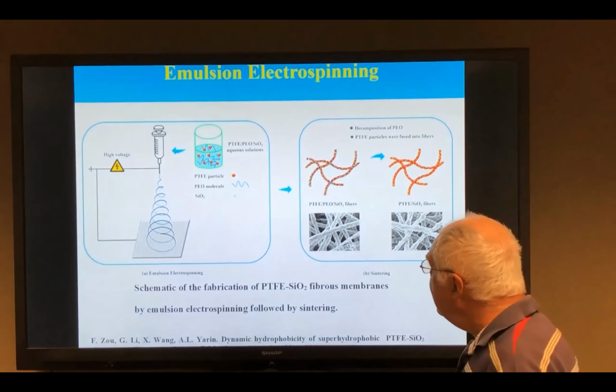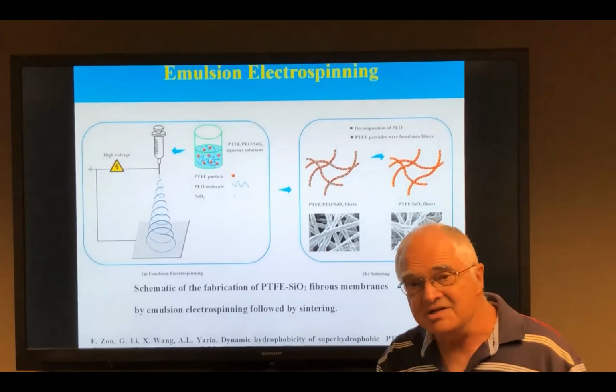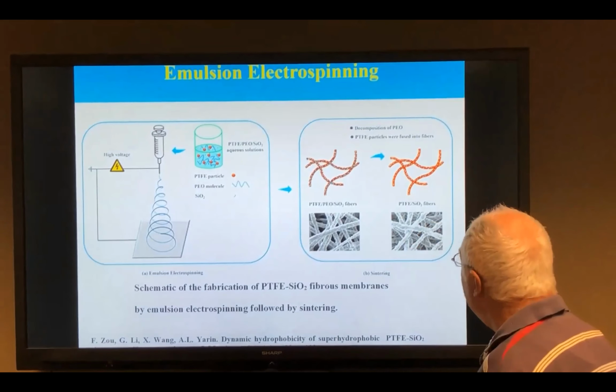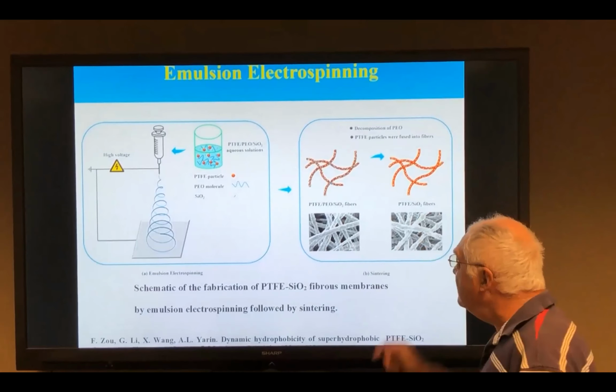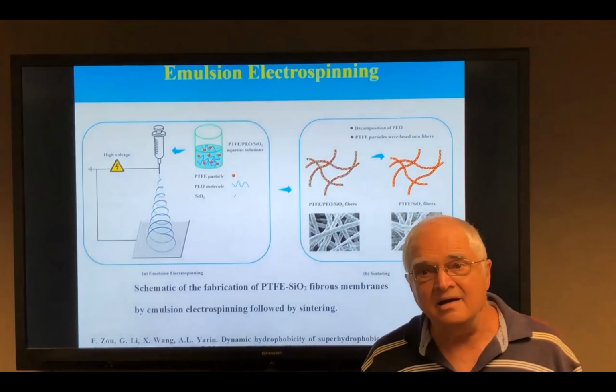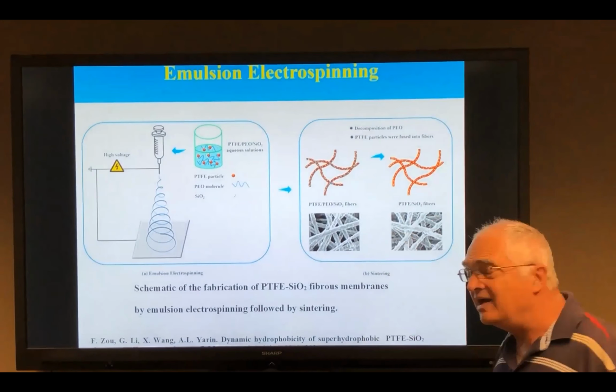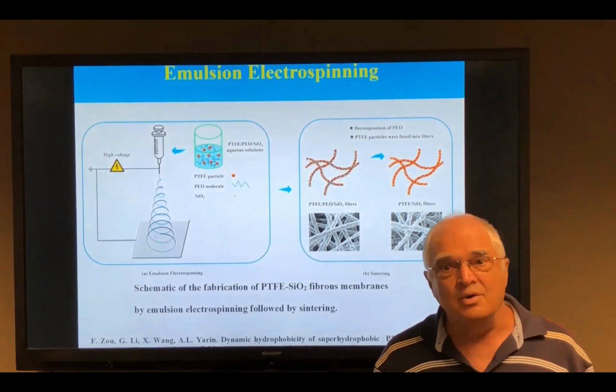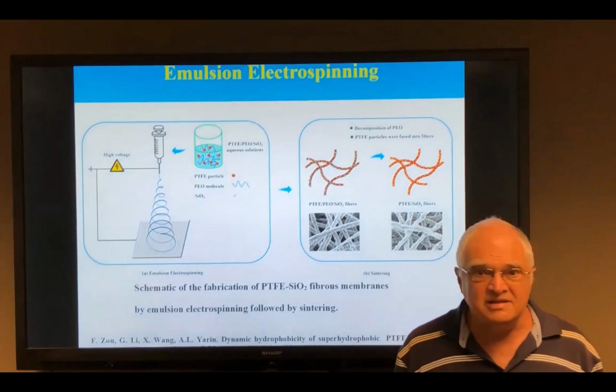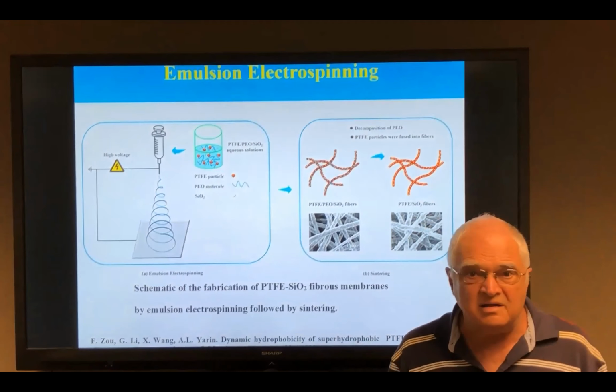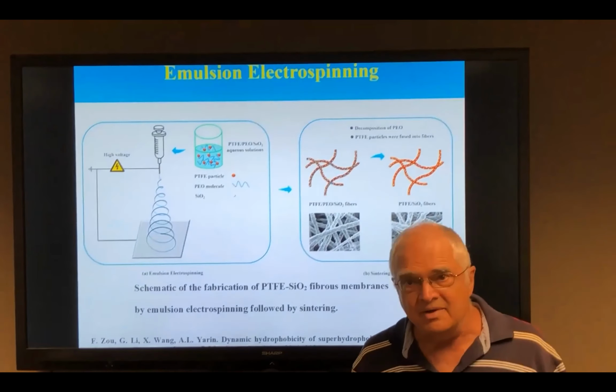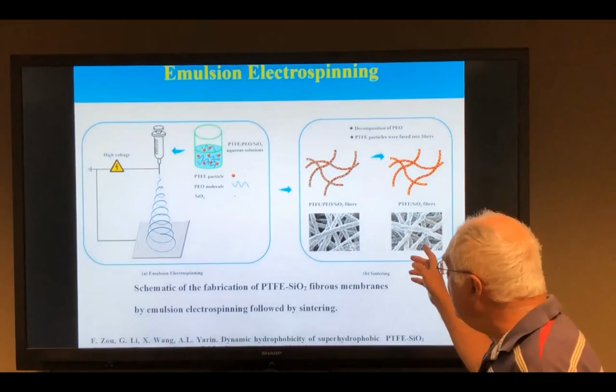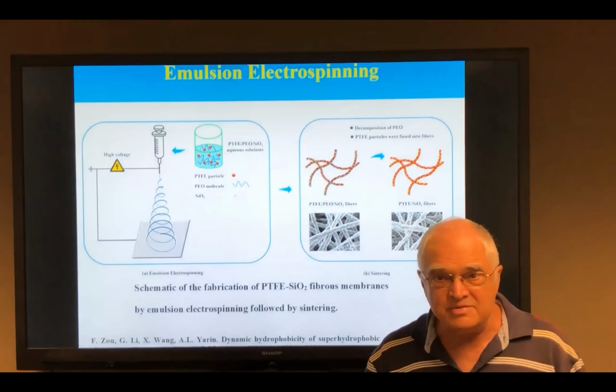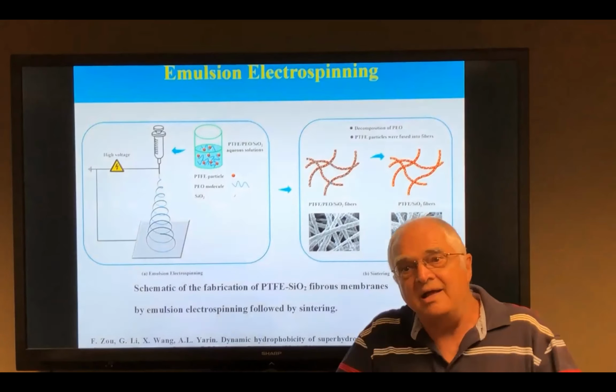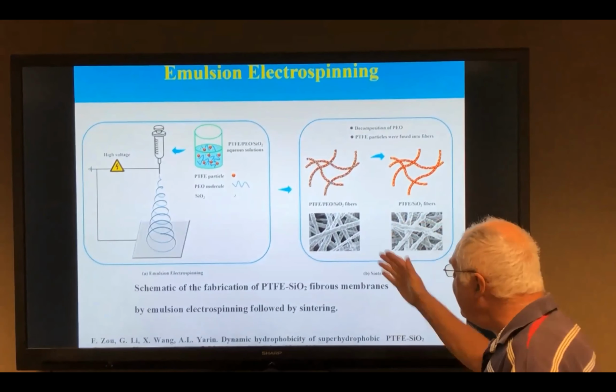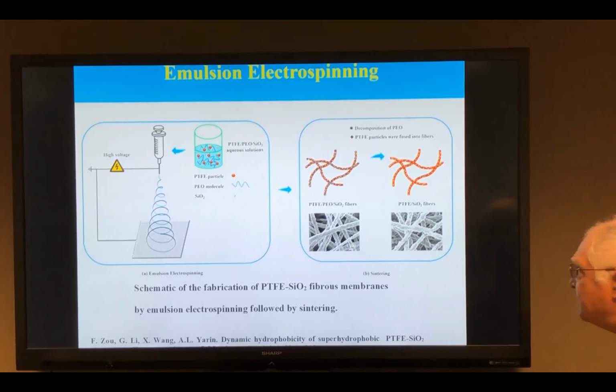This is done by sintering, heating and holding the fibers for quite some time. As a result, you remove PEO and sinter the Teflon particles, so then it becomes Teflon and glass beads inside. What is the reason for the glass beads? When you have sintering, the material typically shrinks, and just before the Teflon is sintered it can be dramatically damaged and disfigured. Therefore glass particles, which are absolutely solid during this process and do not shrink at all, provide structural stability. That's the final result, these membranes. Please go ahead.